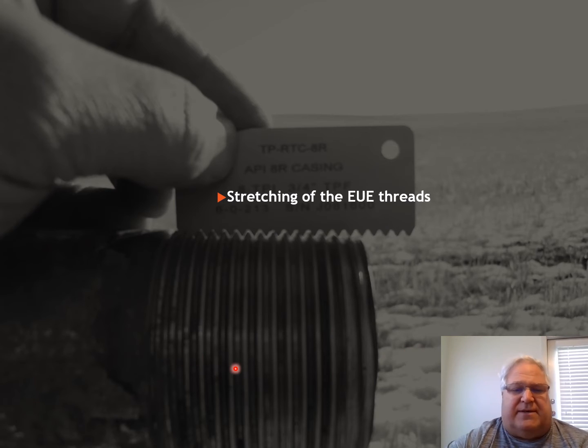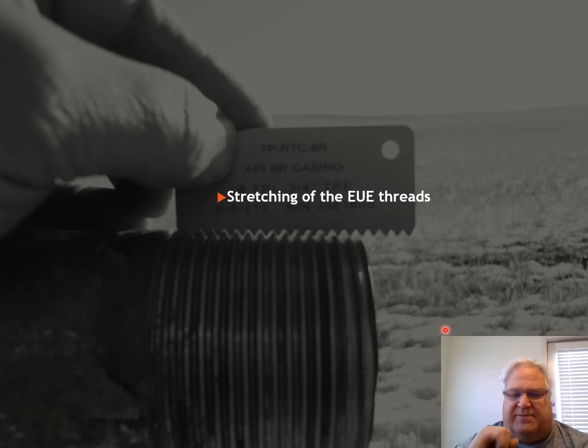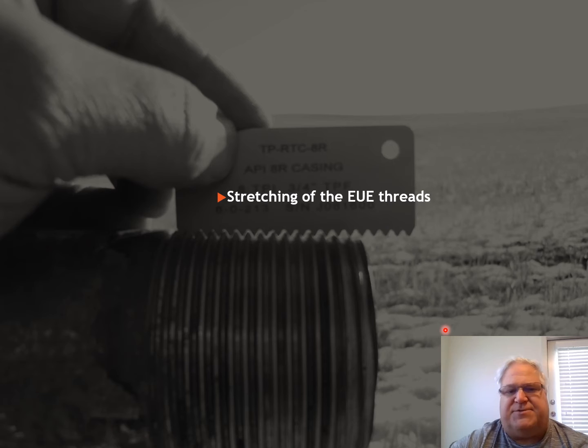Here's another example. Now, these are all different manufacturers. I'm not saying that this is a manufacturing issue or anything. It's an inherent issue that comes with using EUE threads in a plunger lift lubricator. They're not really designed for that impact. They do have pull strength, but they're not designed for that repetitive impact, especially if your top spring has been damaged.